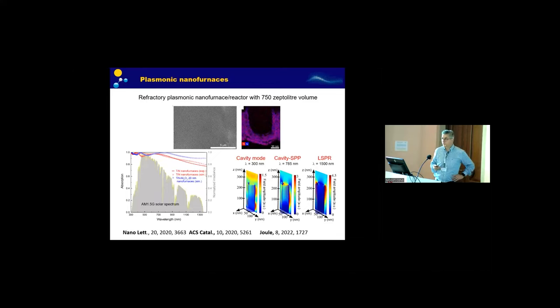So we were interested in titanium nitride nanocavities. Starting from titanium nanotubes made by simple anodization, those nanocavities can reach very high temperature, let's say 600, 700 Celsius, just with a light intensity of 10 suns. So the step change is to really increase the temperature of these nanocavities to the level of conventional catalysis. There are some problems with this material's stability, but you can protect the surface in some way, and then you can load a conventional nanocatalyst, and then you can perform different reactions.